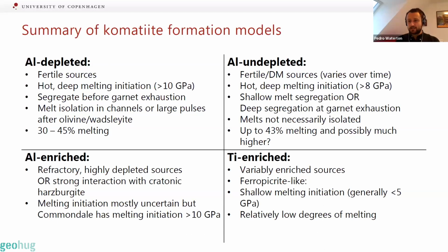So just to summarize everything that I've said there, aluminium-depleted komatiites have fertile sources. They're very, very hot, with high pressures of melting initiation, greater than about 300 kilometers depth. They must segregate before you reach garnet exhaustion to keep that garnet signature. The ideas we came up with are that they either become isolated in channels or large pulses that are formed after crossing the olivine-wadsleyite transition. And they need relatively high degrees of melting, 30 to 45%.